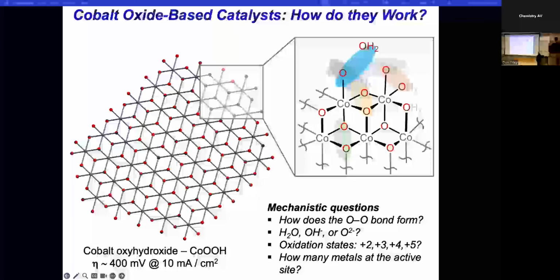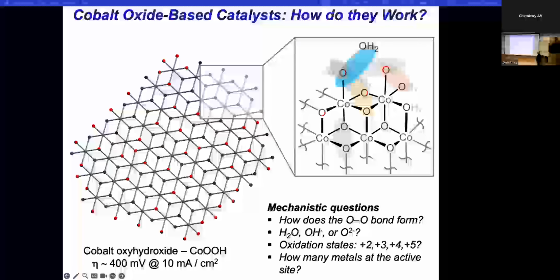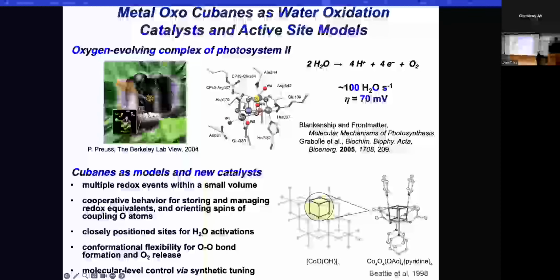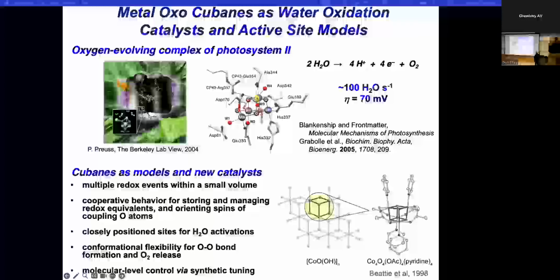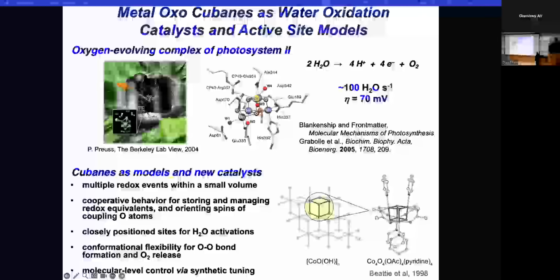And one of the first things we did was design a binucleating ligand that allowed us to put two cobalts in close proximity and bridged by oxygens with terminal oxygen species to interrogate whether or not we form OO bonds. And to cut a long story short, we learned a lot from that system, but we never saw oxygen. So we concluded from that that two cobalts are not enough. And then on further reflection and looking back to the natural system, it made a lot of sense to us that four first row metals makes a lot of sense.